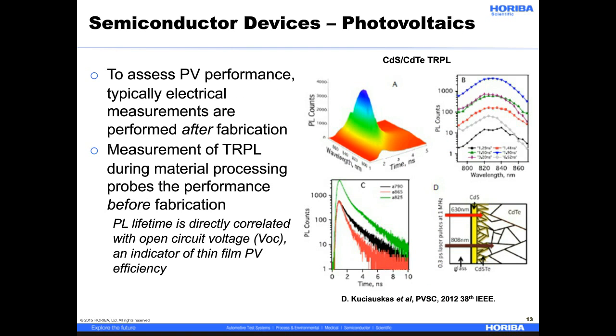Typically, in photovoltaic systems, the quality of the material is assessed by electrical measurements after the device has already been fabricated. This necessarily eliminates the possibility of carrying out any on- or in-line processing during manufacturing. However, by measuring the lifetime of the material using TRPL, the material process can be changed or optimized in real time before fabrication. This is because PL lifetime is directly correlated with the open circuit voltage, an indicator of thin film photovoltaic efficiency. In the example shown here, the system under study is a cadmium sulfide, cadmium telluride photovoltaic device.